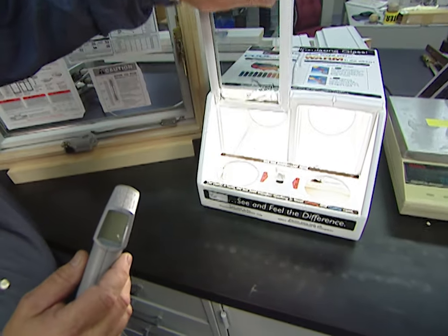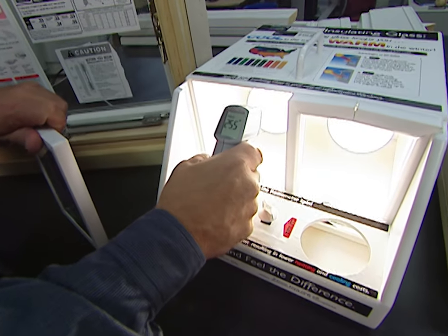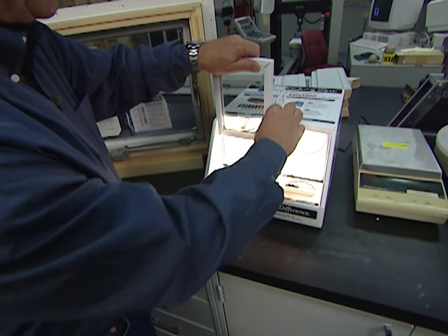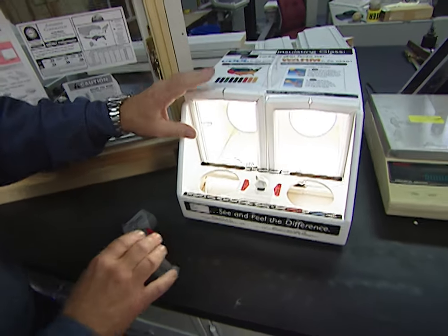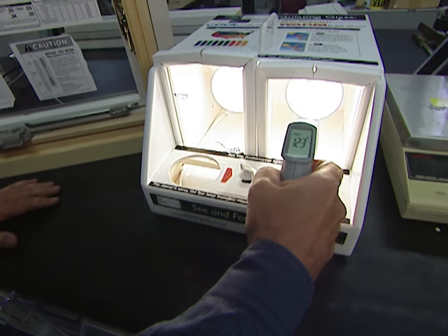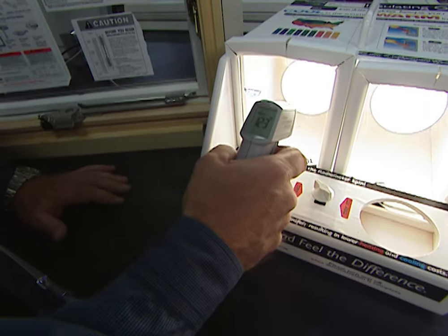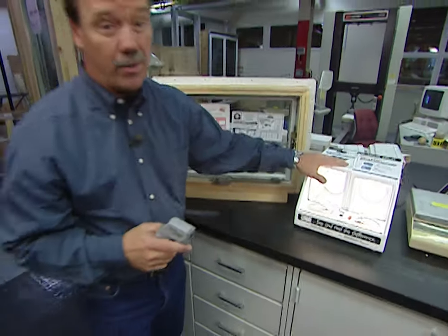What I can do is take the temperature of this sun lamp — as you can see, it's 155 degrees. In this box I have two different types of glazing products: a standard double-pane window and another window with the low-E coating. The standard window reads about 123 degrees, while the window with the coating is about 103 degrees — a full 20 degrees cooler. These low-E coatings really work to help keep heat out of your house in the summer and keep heat in during the winter.